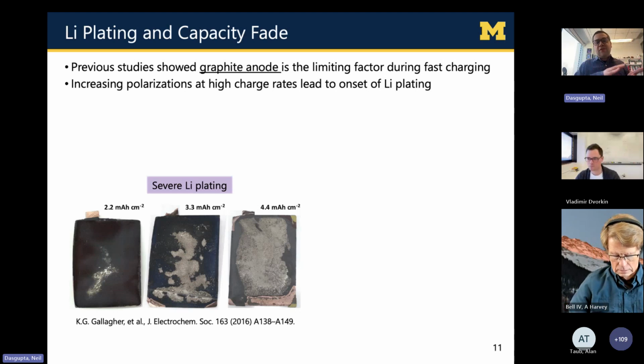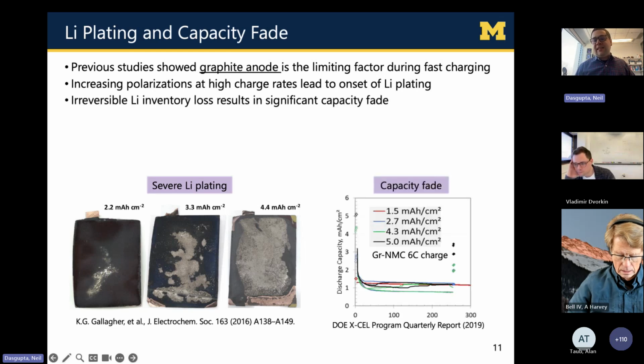And what you see on the surface of this graphite anode, which is normally just this dark black color, is this lithium plating, this metallic shiny lithium that occurs on the surface. Lithium plating is an undesirable side reaction of fast charging of graphite, and this leads to a lot of irreversible behavior. You can see that irreversibility here when you try to charge these batteries at what we call a 6C rate. If you're not familiar with C rate in batteries, the higher the C rate, the faster you're charging the battery. So a 6C rate corresponds to a 10-minute recharging time.